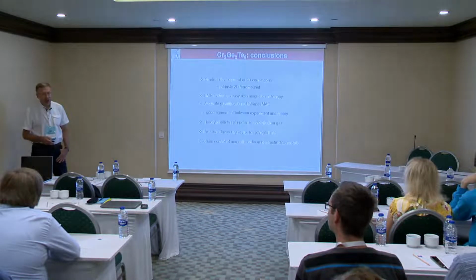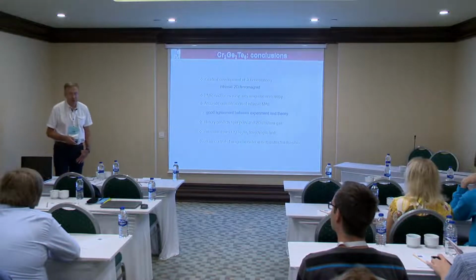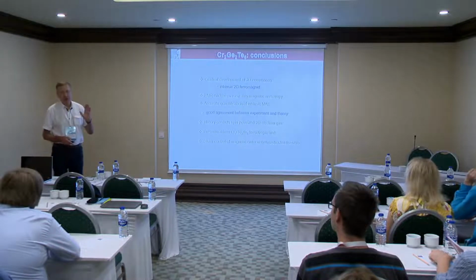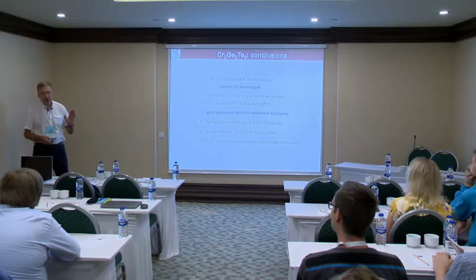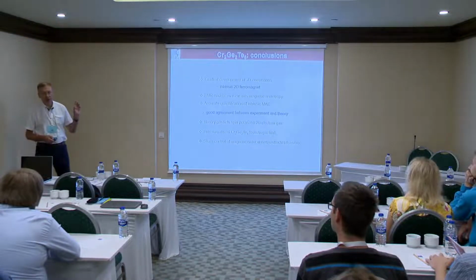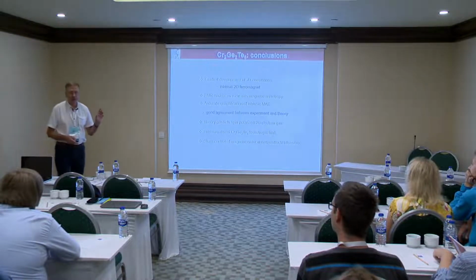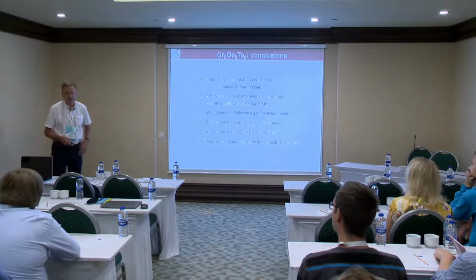As soon as we apply pressure in the pressure cell, we have some unwanted distortions of the ESR line. Therefore, we could reliably determine the resonant field, but the line shape is distorted. And therefore, the determination of the width is getting problematic. So we didn't attempt to do that.